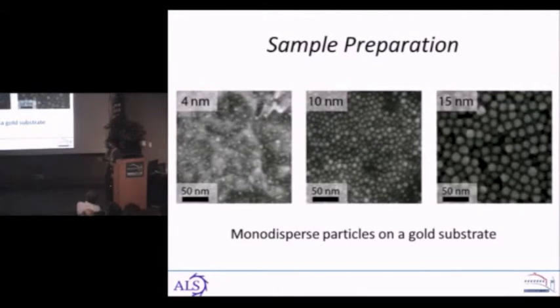It's also important that the cobalt is well dispersed on the gold because you don't want the particles to be too closely clustered together, because then they might sinter and destroy the catalyst over the course of the reaction. But you want it to be dense enough that you get a good signal on the sample.